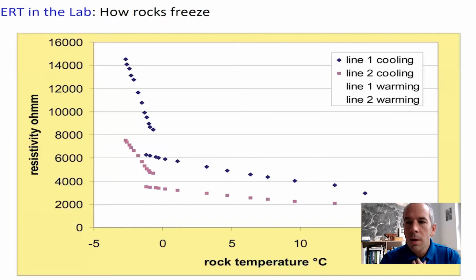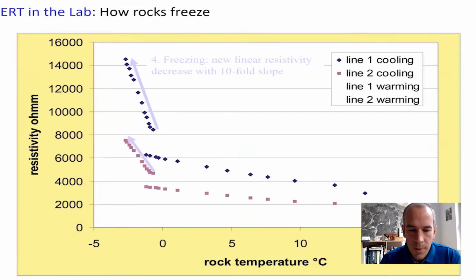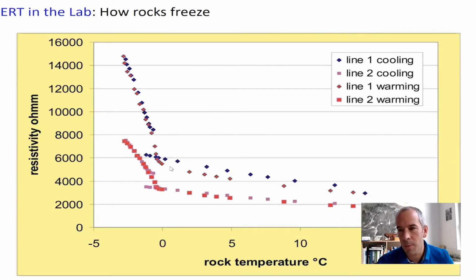The first remarkable change, I go pretty quickly over that, is that the electrical resistivity changes quite a lot. So if that is the unfrozen resistivity, this is the electrical resistivity that changes gradually. Upon freezing, suddenly the electricity can't penetrate through the rock very well anymore because it uses the water in the pores to penetrate through it. And if the water in the pores starts to freeze, there are decreasingly pathways for the electricity in the rock. So we can see a very strong increase in the resistivity upon freezing, which is not exactly at 0 degrees, but a little bit lower due to several effects on this freezing. Okay, I go quickly over this.